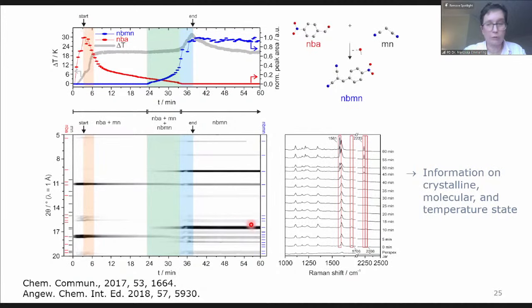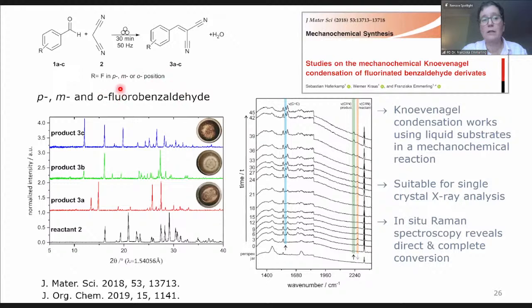Okay, so we then went on looking at different Knoevenagel condensations, looking at differently fluorinated aldehydes. These are interesting because those are all liquid. But nevertheless, it's also possible to monitor that reaction. And we also got a new compound that was not described before. And we could actually isolate a single crystal material and measure it directly from the milling vessel.